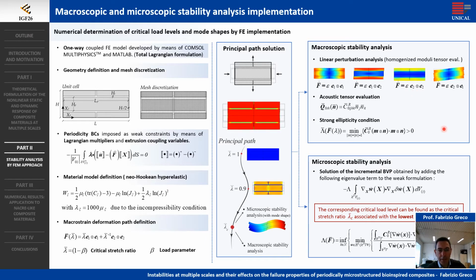The microscopic stability analysis has been carried out by discretizing the variational linear eigenvalue problem characterizing the microscopic stability, while the macroscopic stability analysis has been carried out by monitoring the value of the load parameter along the prescribed macrodeformation path, where the strong ellipticity condition for the homogenized moduli tensor first fails.